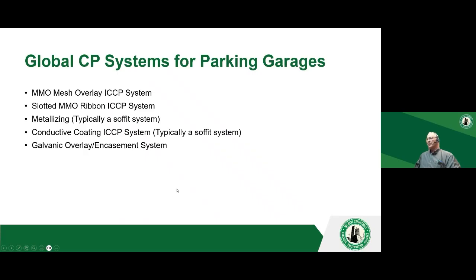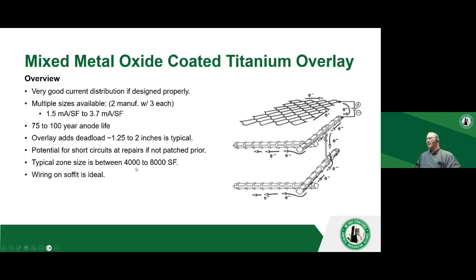And then we look for a global system, the ICCP systems. And what we're doing here is we're going to put mixed metal oxide as one of them. Mixed metal oxide is a mesh anode that's put above the concrete surface. You're putting an overlay in, and that's connected to the reinforcing to throw current to it. Now, what happens with this is it protects it.